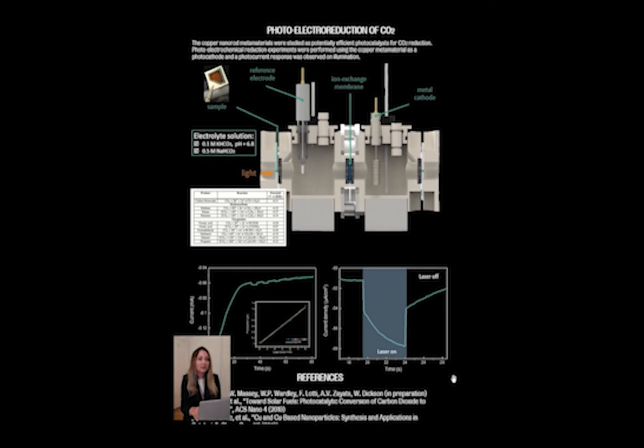The electrochemical measurements were performed using an electrochemical H cell, where copper nanorod sample is our cathode, where carbon dioxide reduction occurs. We also studied the photoelectrochemical behavior of copper nanorod catalyst. Under illumination with red laser, the current was enhanced in magnitude when using negative potential. That means that the incident light can actually promote reduction reaction when plasmonic catalyst is used.